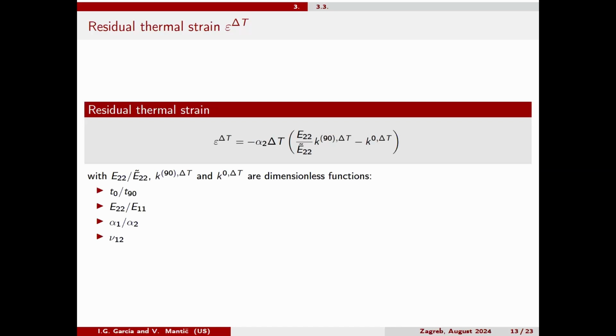You can see that it's linear with the increment of temperature, that in our case will be negative, because it will be the difference between the autoclave curing temperature and the service temperature. And we have also some functions that are analytical and depend on the material and laminate properties that you can see here.